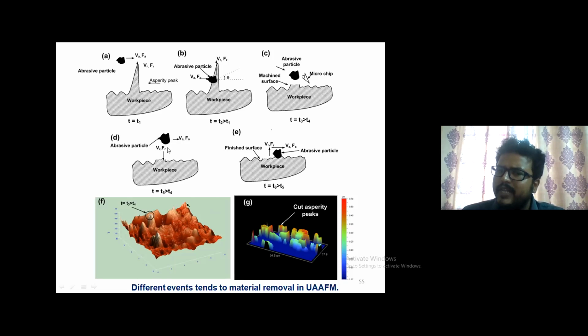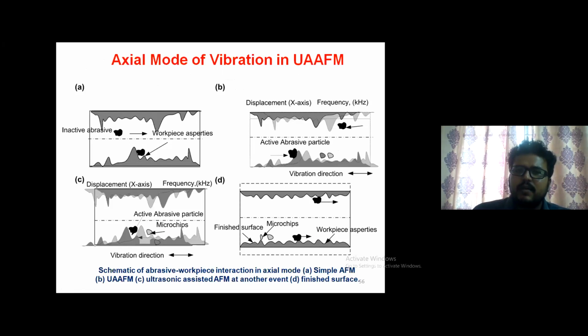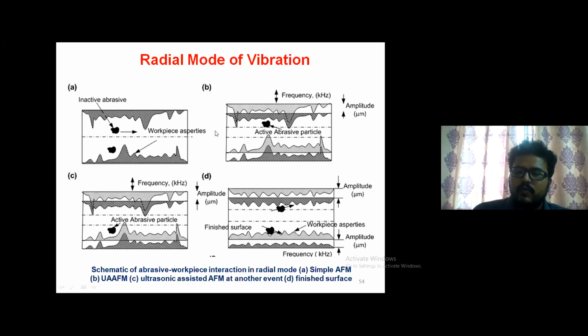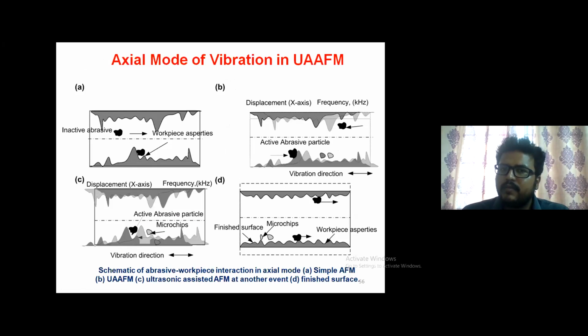It will be in milligrams. So the part which is cut will be in very small microchips. So we cut microchips and we do nano finishing using this process. So by changing the mode, see for example, here is one interesting study. In the first case, the actuator is fixed, meaning the vibration of the workpiece is perpendicular to the flow direction, that is, the actuator is fixed radially, and we recorded the result. Similarly, we observed when you fix the actuator axially, what happens to your response?